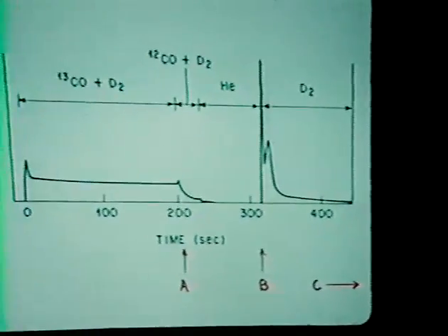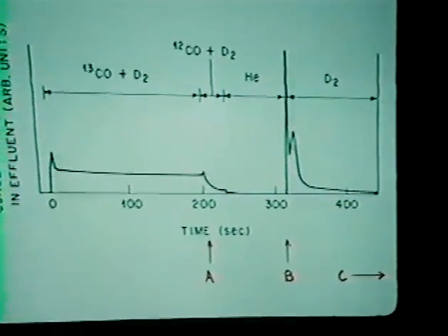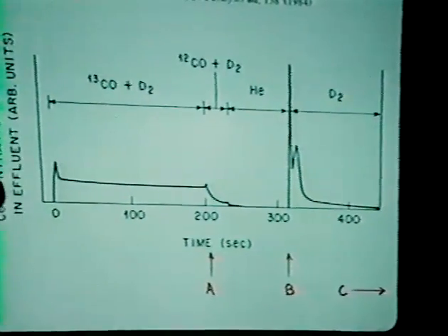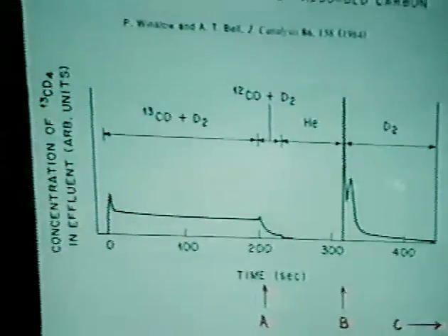A note about this quenching process, it's inevitable that the state of the carbon changes a little bit. We take the reactor, which is at 200 degrees C or so, and bring it down very quickly in temperature. First turn off the flow, then bring it down in temperature, seal it off, and go do the NMR. We've done the studies on this that we can bring this down, let it sit for a day or so, bring it back up in temperature, turn on the flow, and exactly resume this transient response curve that we've seen here before. So we know whatever changes we're making are reversible on these samples, but we aren't sure to what degree the changes are going to be affecting the spectra we see. I think you'll see later from the type of species that we detect, these are not species that are going to readily be converted back and forth